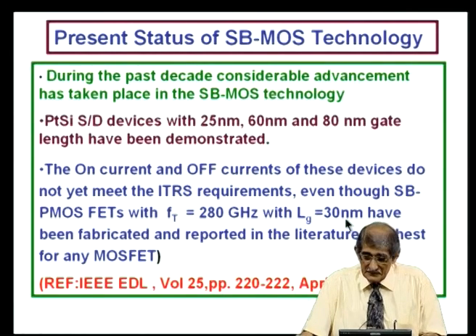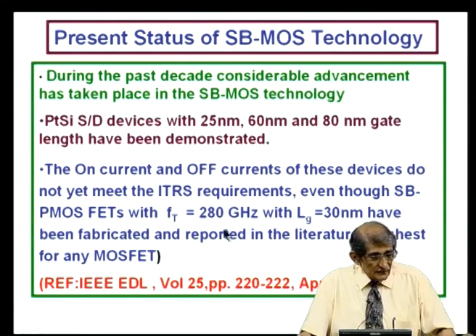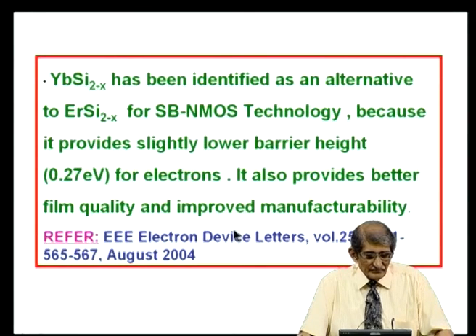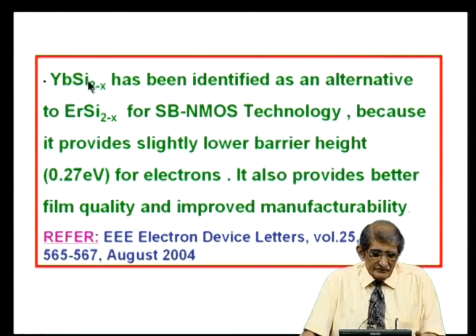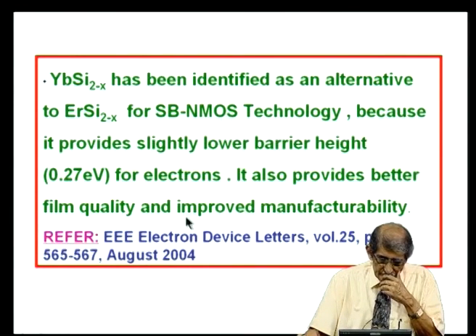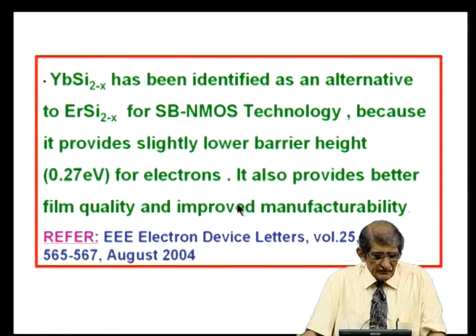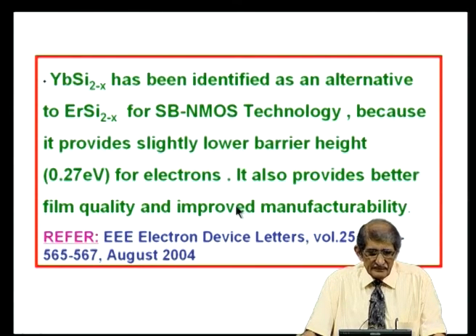30 nanometer gate lengths have been fabricated, even as early as 2004. P-channel devices have been fabricated with the highest frequency for any MOSFET, because of that low resistance etcetera. P-channel, not n-channel. Ytterbium silicide has been identified as an alternative to other materials because barrier height is low. So, that is one of the things people have been looking at to some degree of success.